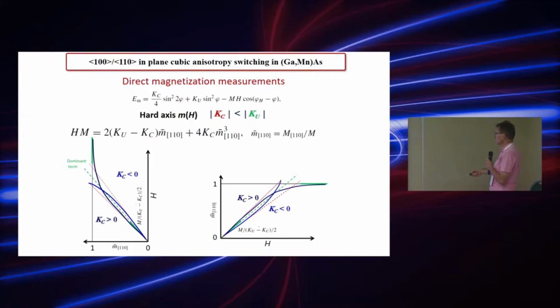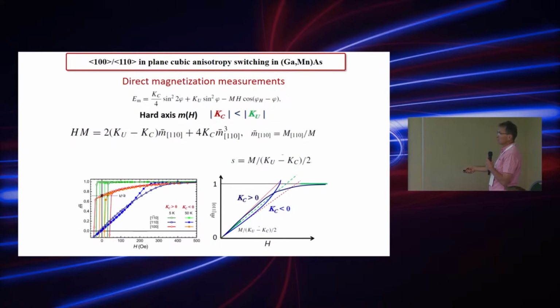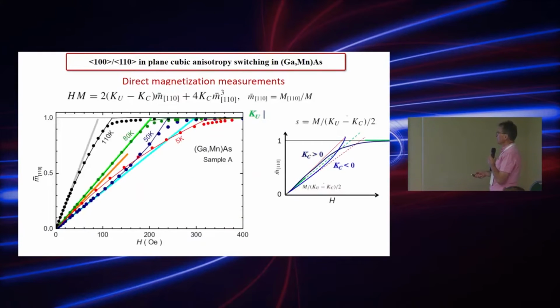So now I will just rotate this to the normal experimental units, and we find something that resembles very strongly our experimental findings, which look like that. So the conclusion of this part is that this change of the character of the hard axis magnetization from convex to concave indeed reflects the change of the sign of the cubic anisotropy. And now we can, for example, compare the results for a few temperatures. So we plot here, now working in the standard coordinates, magnetic field on the x-axis and reduced magnetization on the y-axis.